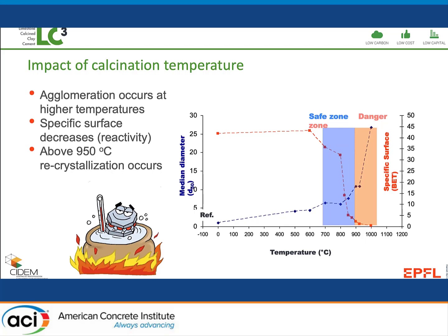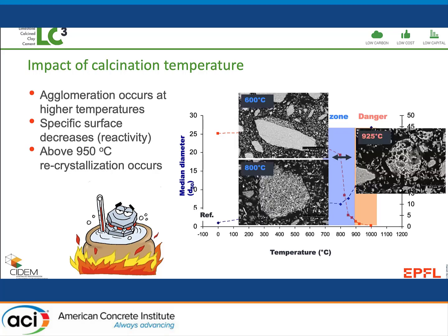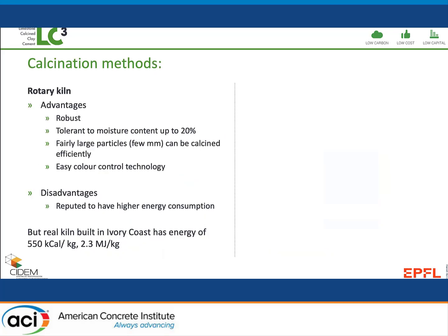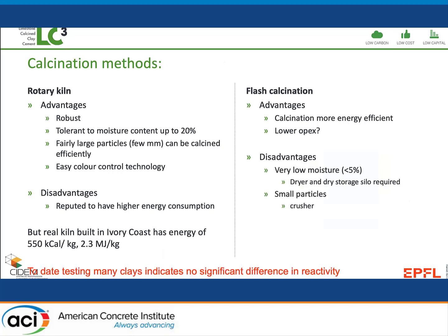So many people say, well, can we use fire-clay bricks? Well, the answer is really no, because generally fire-clay bricks have gone up to a temperature more in the range of 950. And this just shows this agglomeration process. So calcination methods, Jesper already said, you can use rotary kiln, you can use flash calcination. There are various advantages or disadvantages. We found, like he did, that really it makes very little difference to the reactivity.